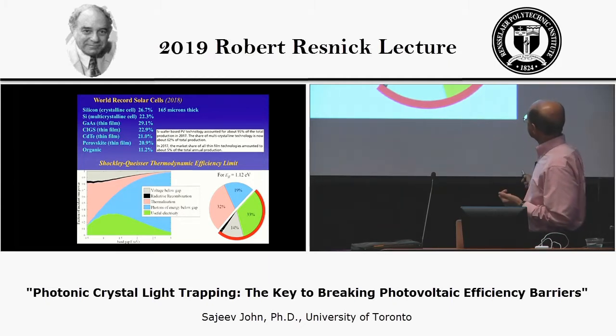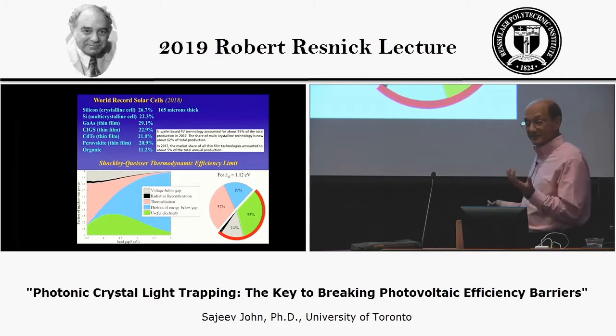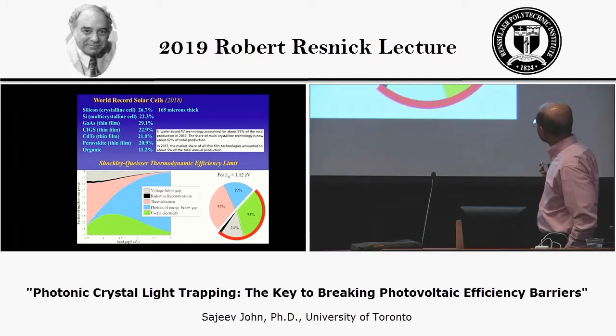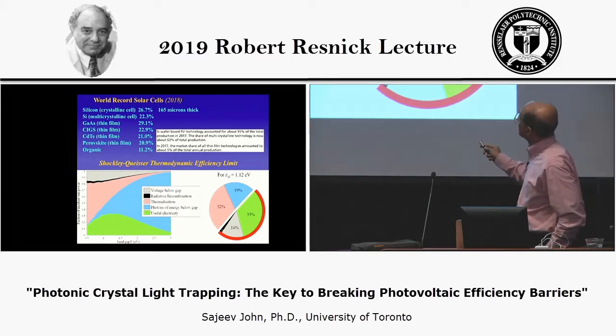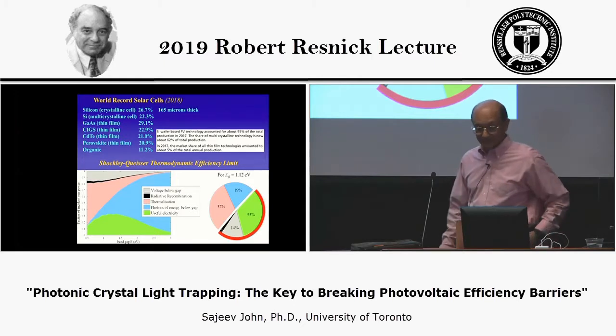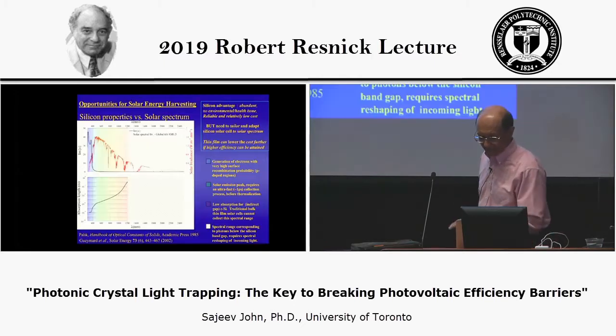So this is the objective. Can we get as close as possible to this? This requires that 100% of the sunlight above the band gap should be absorbed. That's also something that is impossible to achieve. So typically silicon cells have much less efficiency, and as you can see here, the current world record is only at 26.7%.